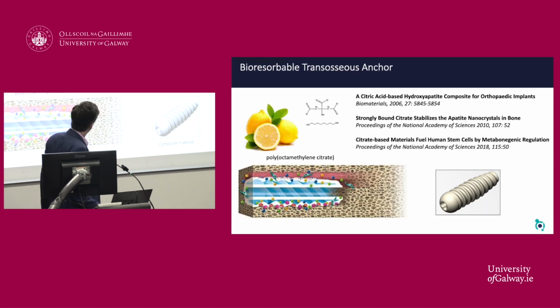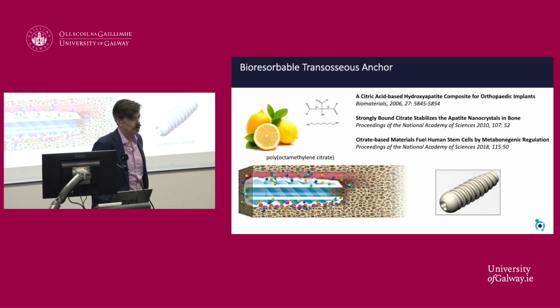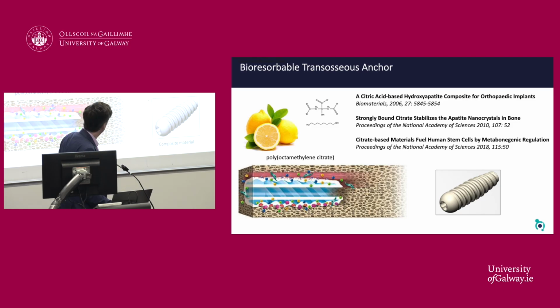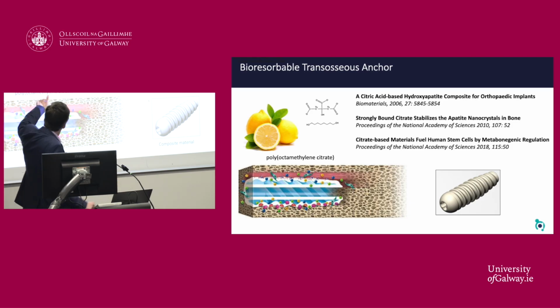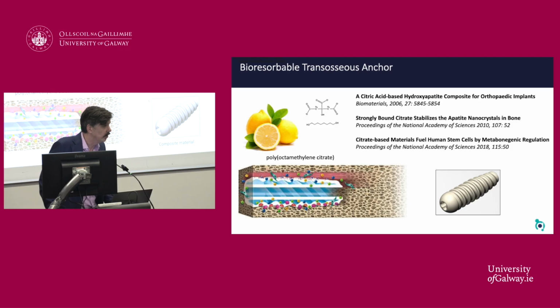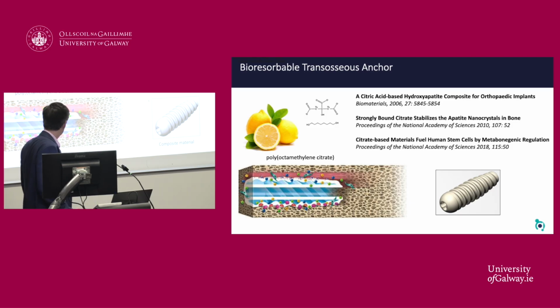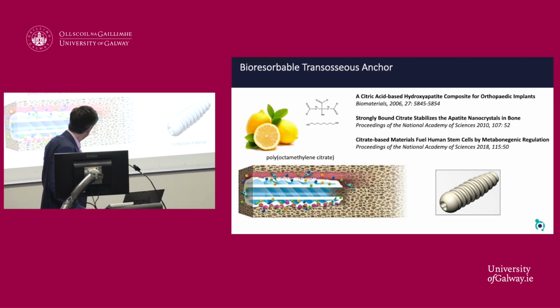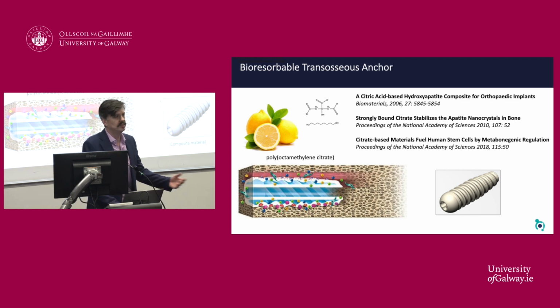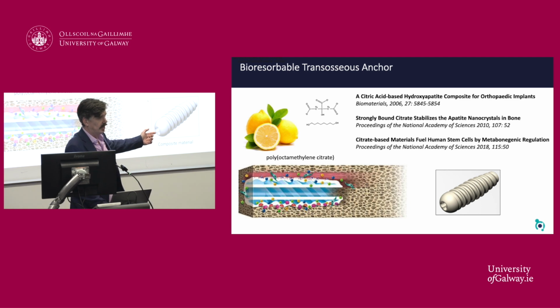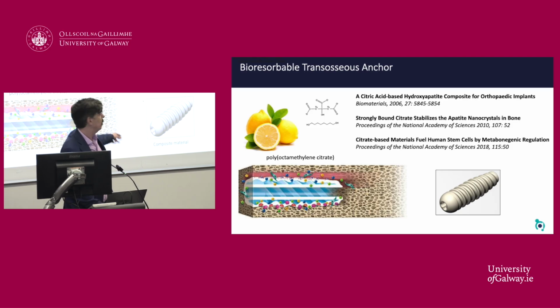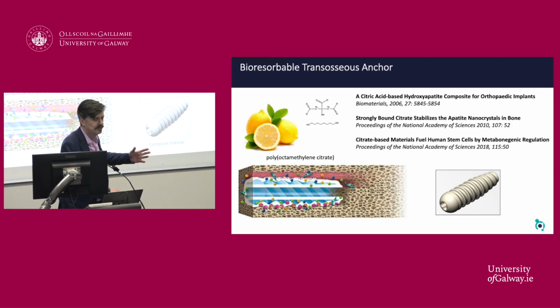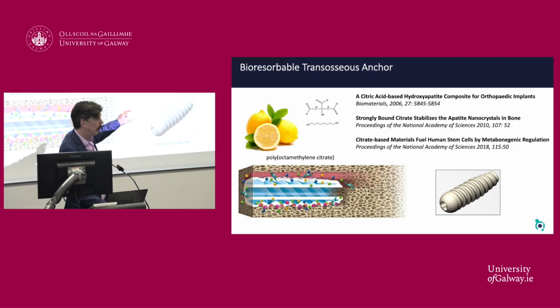Okay, so what do we want to do? We wanted to create a better tendon anchor, essentially. So we turned to a biomaterial that had been published many years before. And this is really nice for several reasons. We made a composite material out of citric acid. Citric acid is what makes lemons nice and tangy and tart. We created a polymer out of this material. It's called poly(octamethylene citrate). And we took that and we mixed it with hydroxyapatite powder. Hydroxyapatite is a mineral found in bone tissue. It's a microscale powder, so a very fine powder. We mixed it with our polymer, our lemon polymer, citrate polymer, and we created a really stiff, bone-like material.